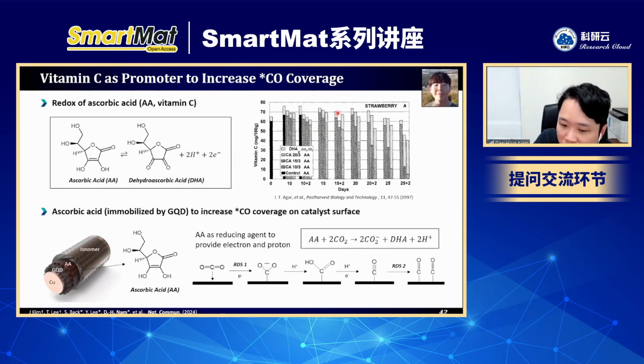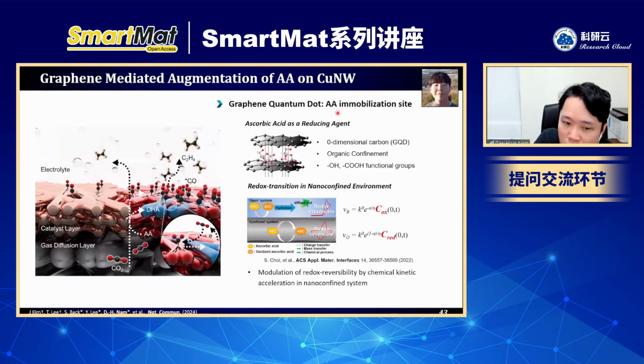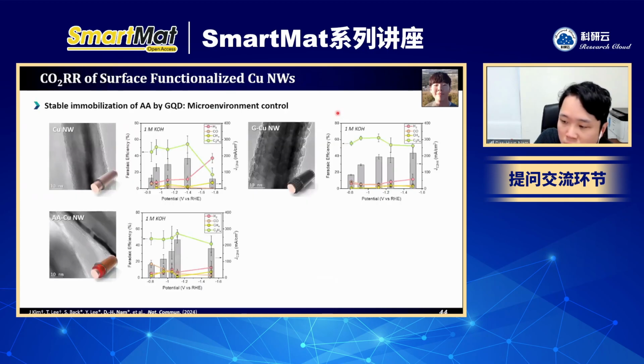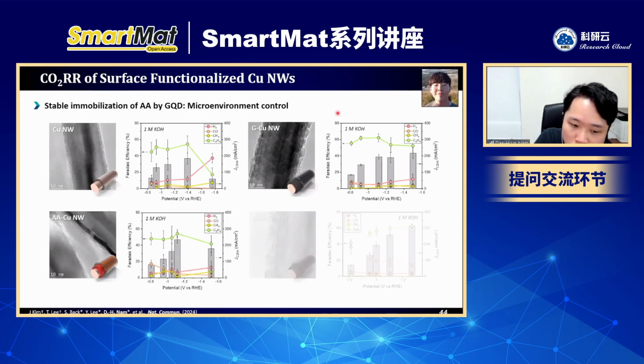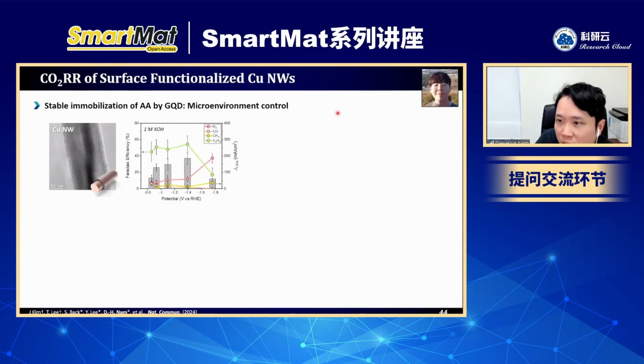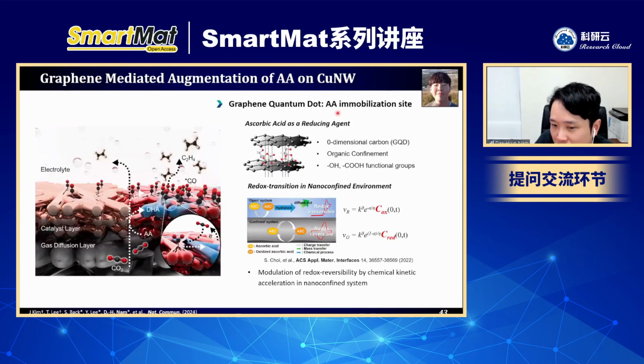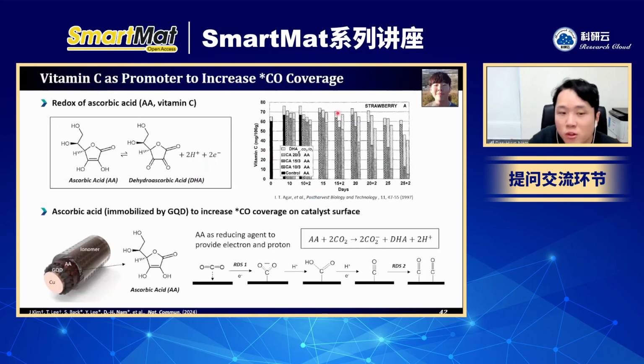Because the first one, the spillover effect has also been focused on for CO, right? Because if we apply silver or iron porphyrin, which can produce CO from CO2, then this will be very effective for controlling the selectivity. That is part one. And for this part, I also agree this can be a spillover point of view. So we try to use ascorbic acid to promote proton and electron transfer to enhance the CO2 to CO conversion, because this CO is very important for the C-C coupling, right?